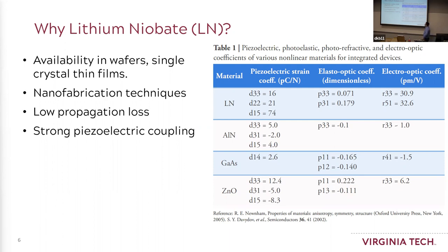And the other thing is the strong piezoelectric coupling. You want to make transducers, so this piezoelectric coupling is important. It is strong. You can see here, compare the numbers: the piezoelectric coefficient of this material is almost one order of magnitude larger than the other materials.